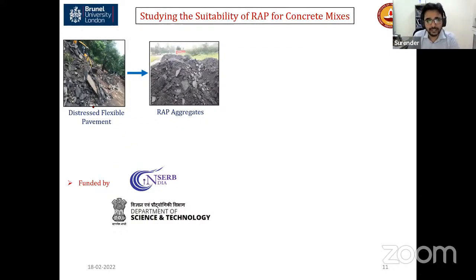Reclaimed asphalt pavement means an existing asphalt pavement, or in India we call it a flexible pavement, which normally after 1 or 2 years of construction starts showing distresses, especially in areas where we have good rainfall. So when you remove this material, it is again an aggregate similar to recycled concrete aggregate. It also consists of the pristine aggregate, but totally surrounded by an asphalt film. The asphalt film could be around 6 to 10 micrometers, right?